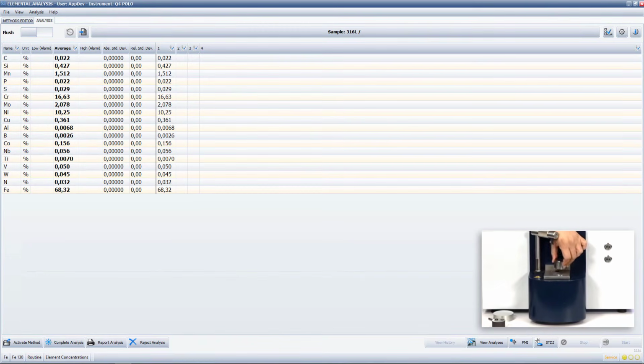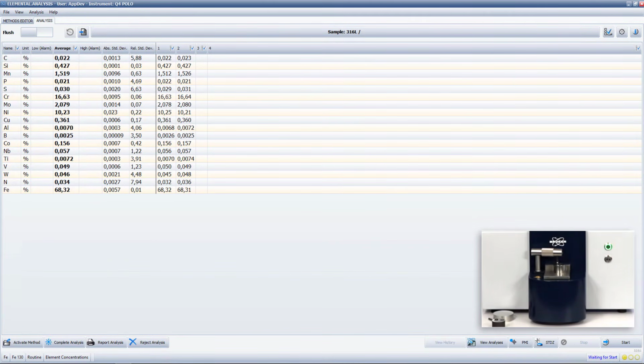200 series has a higher manganese and nitrogen content and a lower nickel concentration. While this leads to an improvement in yield strength, it also weakens the corrosion resistance. 300 series, on the other hand, has better corrosion resistance. The best known grade in the 300 series is 304, which has around 18% chromium and from 8% to 10% nickel. Type 316 is probably the most common austenitic stainless steel. It has approximately 2% molybdenum in it, and this gives it a better corrosion resistance than type 304.